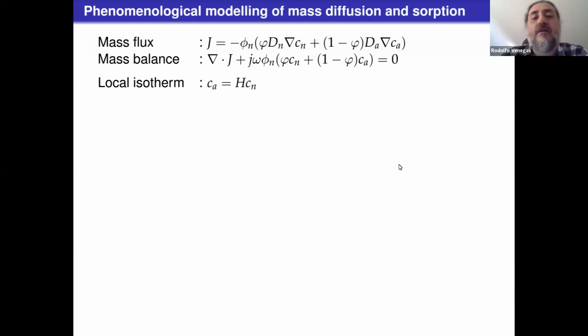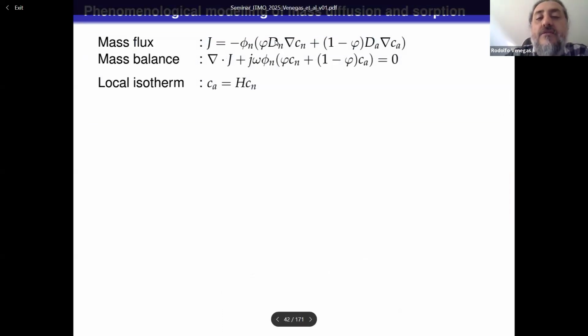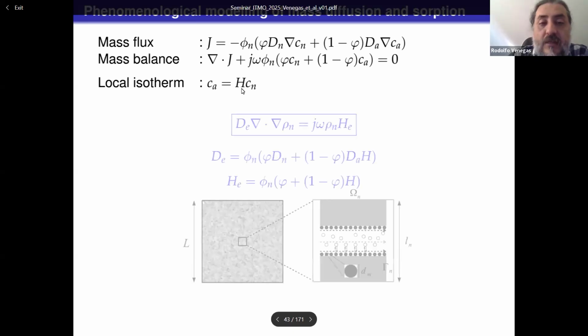So how do we model this? We consider mass flux related to a diffusion coefficient for the molecules that are in the bulk of the pores with a concentration Cn, and also another mechanism of diffusion, in this case the surface diffusion, of the molecules that are adsorbed with a concentration Ca. We carry out a mass balance where the divergence of the mass flux is balanced by this effective concentration, and we relate the concentration of the adsorbed molecules with the concentration of the free molecules through a local isotherm of linear type, where H is the linearity constant.